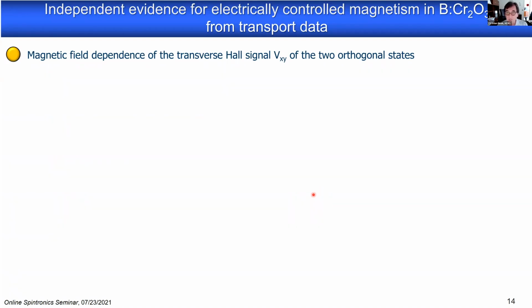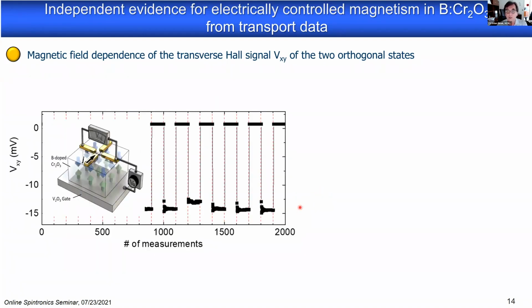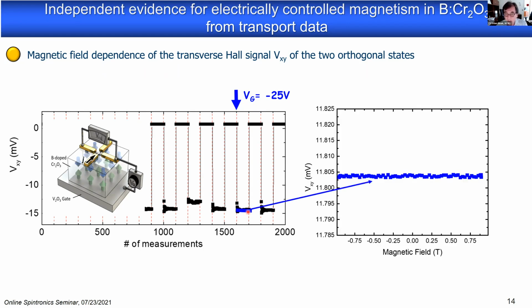We looked at transport data and tried to figure out how we can show that this has something to do with magnetism. Well, we measured the magnetic field dependence in these different states. So first, we switch it into a state where there is a significant Hall voltage, very similar to the situation in pure chromia. And if you do that, very similar to pure chromia, you hardly see any magnetic field dependence because we are here at room temperature, which is substantially below the Néel temperature of boron-doped chromia.